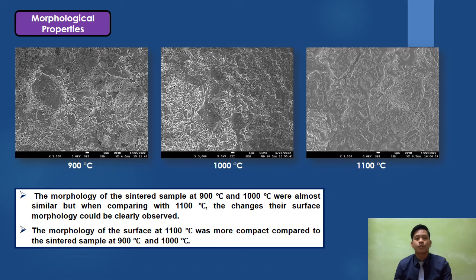For the morphology properties result, the same images of the sintered samples were taken at a magnification of 3000. The morphology of the sintered samples at 900 degrees Celsius and 1000 degrees Celsius were almost similar, but when comparing with 1100 degrees Celsius, the changes in their surface morphology could be clearly observed. This was due to the difference in surface compactness of the sintered samples. The morphology of the surface at 1100 degrees Celsius was more compact compared to the sintered samples at 900 degrees Celsius and 1000 degrees Celsius.